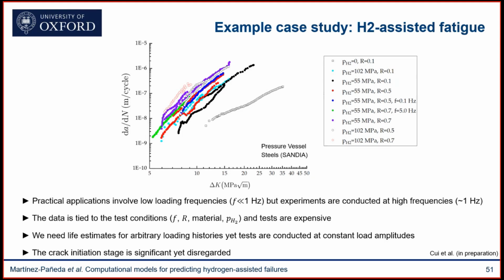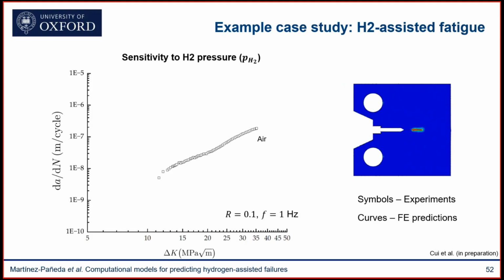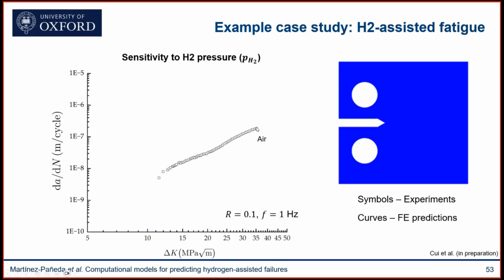So we said, okay, the good thing is that we have data to test our model. Let's see how our model behaves. So the first thing is that we try to calibrate our model with the response in air. So this is, again, as I said, fatigue crack growth curves versus applied frequency. This is the Paris law behavior. This is for a given load ratio and frequency. So we run our experiments. We basically subject our compact tension samples to cyclic loading conditions. As you can see there, we propagate a crack, and we measure the speed at which that crack is propagating. And we know the fracture toughness of the material, so we just need to calibrate the fatigue degradation function, and then we're able to show that, by calibrating this fatigue degradation function, we're able to capture how this material behaves in the absence of hydrogen.